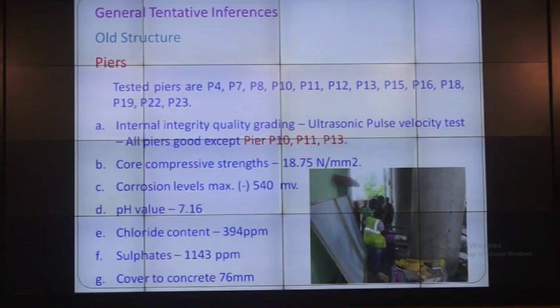Corrosion levels, negative millivolts: I was telling you about 350, whereas here it is 540 millivolts. Please note one more point, an extremely important point. The pH value of about 10 or 20 samples we have taken from the structure, the lowest was 7.16 as the pH value of concrete. Unacceptable at all. I have not seen such a low pH. Yesterday, that's the reason I was telling you about the pH values. A 20-year-old structure has come down to such a 7.16. You can't expect the life of the structure with such low pH values.